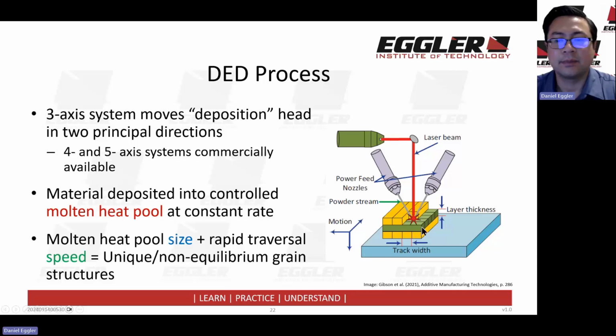As you can see, very similar, but what we have is the melt pool. Right, so similar to powder bed fusion, because we're working with lasers, we can control a melt pool, and because we control the melt pool, similar to powder bed fusion, we control the phases as the material cools down, and we can also, as a result, have very interesting, unique or non-equilibrium grain structures. If you have done any metallurgy, you'll know about phase diagrams and phase transition diagrams. But the ability to control the melt pool controls the material properties. So we can have all kinds of interesting and unique material composition possibilities using directed energy deposition.